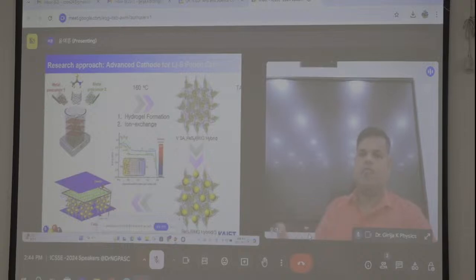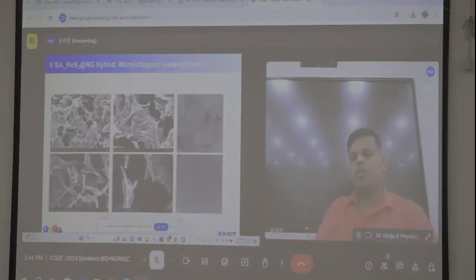Even though, when we are going for lithium sulfur battery, there are a lot of issues during the charging discharge process. The lithium polysulfide formation is the big issue. Therefore the kinetics will be slow, because the fast kinetics may be reduced after a few charge discharge cycles. So people are developing highly stable materials during the charge discharge process, against volume expansion, for getting high energy density and power density.